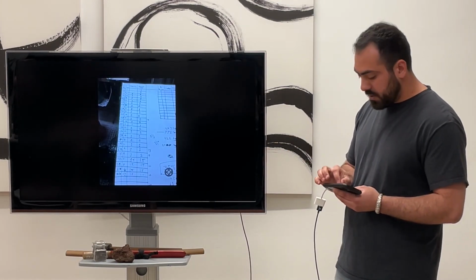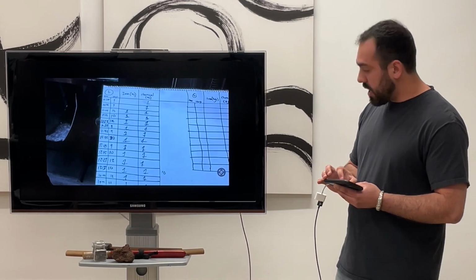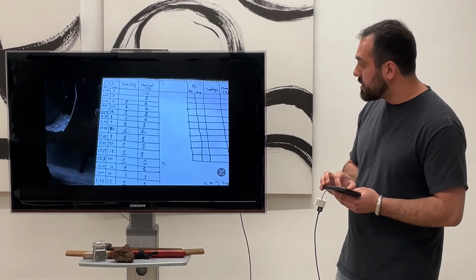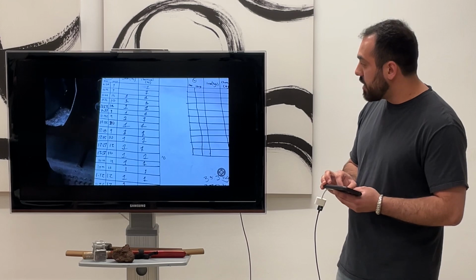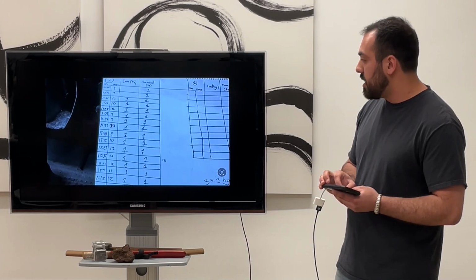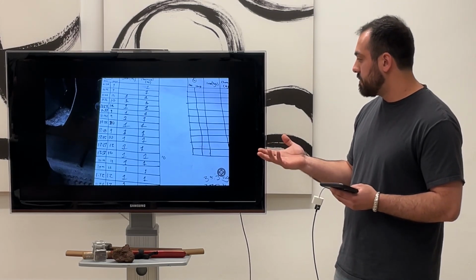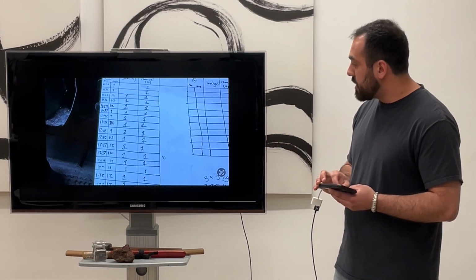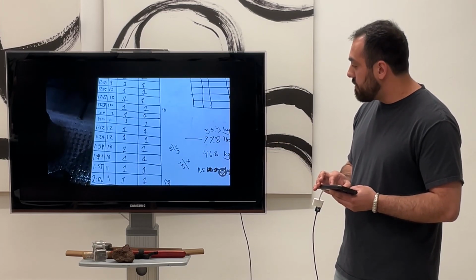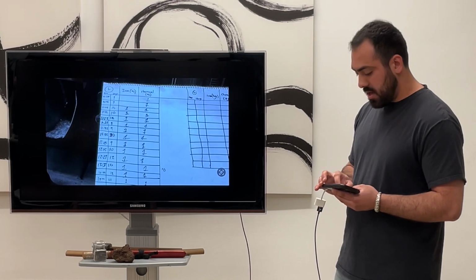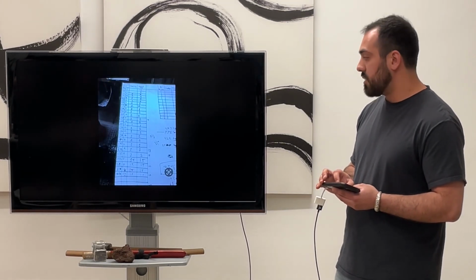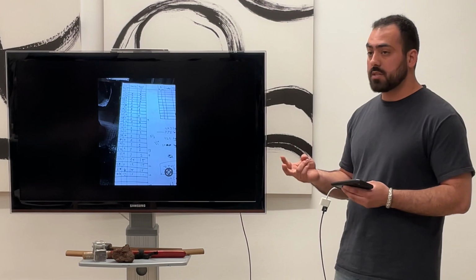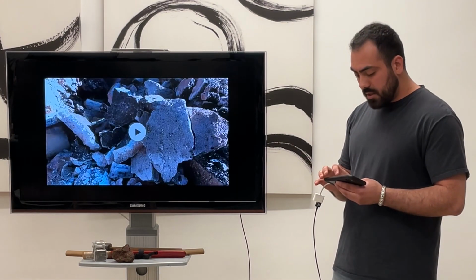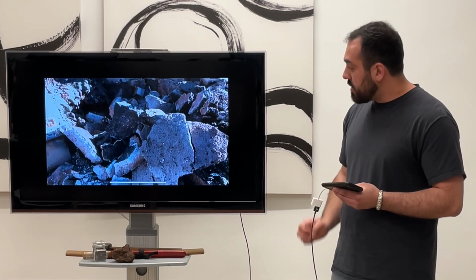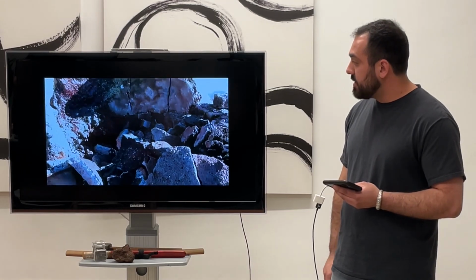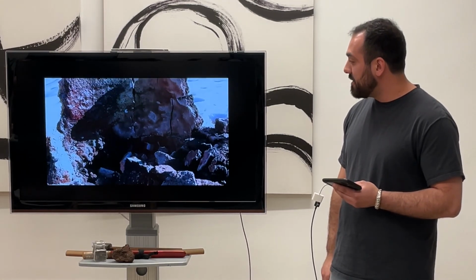This is kind of a rough table to show how we keep track of it. It's basically just every 9 or 10 minutes we're putting a kilogram of iron oxide in, as well as a kilo of charcoal. Near the end of the run, we usually double up and start charging it a little bit quicker, either at double the pace or at 1.5 times the pace. This was the day after, what was left of our little furnace.